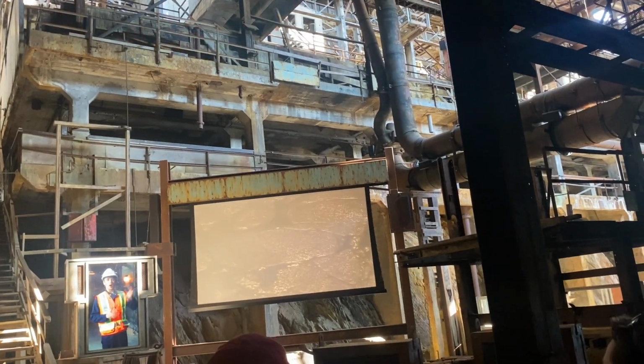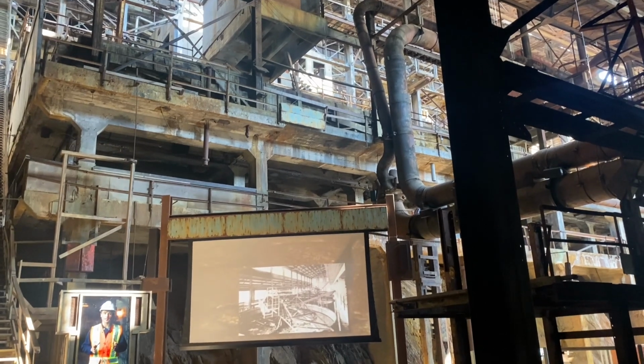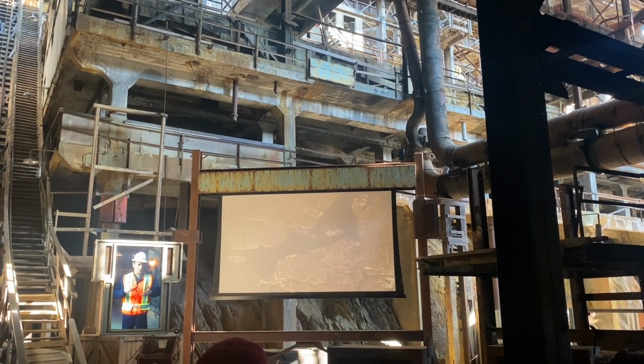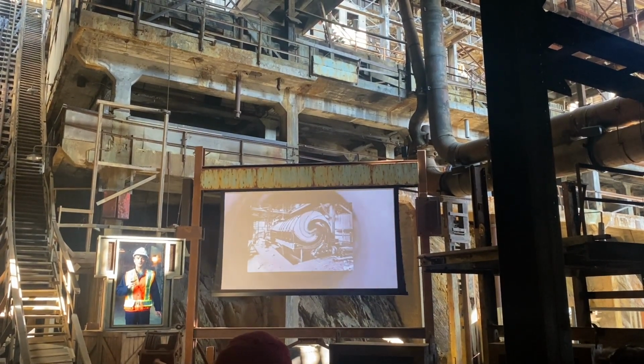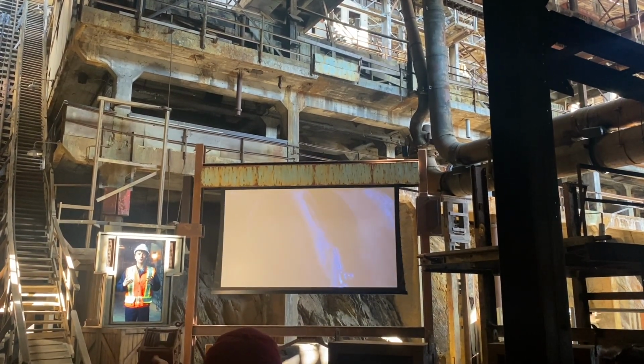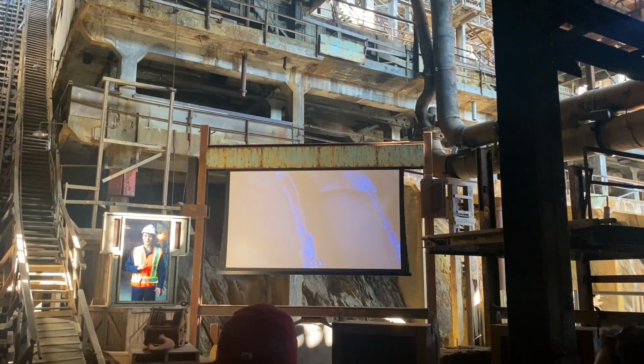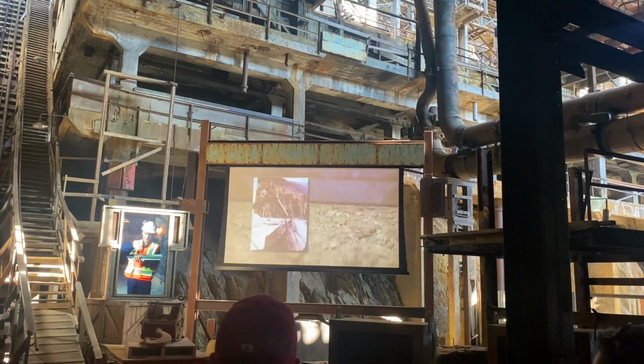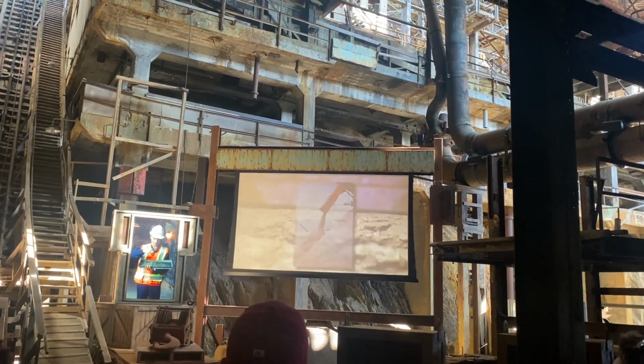The 4th stage, dewatering, happened right over there. The froth was piped into large wooden thickening tanks where this time the copper minerals settled to the bottom. This muddy mixture would then be piped into vats where the water was sucked out through canvas filters, leaving a sort of mineral cake behind called copper concentrate. But not the sort of cake you want to put a candle in, because this is how it looked. This is what was sent to the smelters to be refined into pure copper metal.